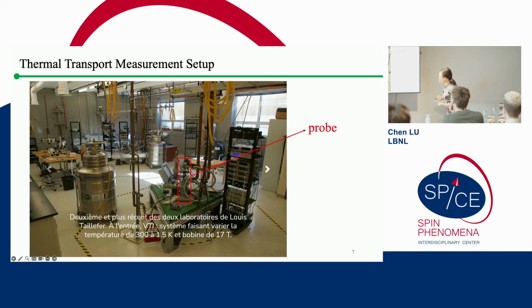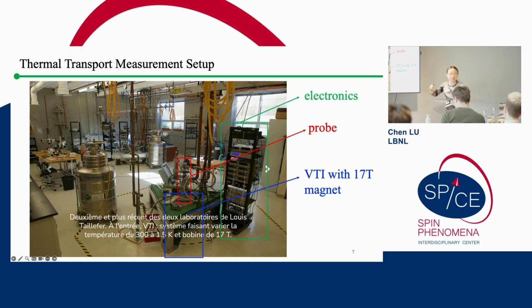For the type of system that we conduct our thermal transport measurement in, we usually use something called a variable temperature insert system, which is a cryostat that goes from 1.5K to 300K, and it is usually equipped with a very strong magnet, because we need a very strong field to actually distinguish a lot of the thermal Hall effect in the material that we try to study. And you put a probe inside the VTI and then apply field. And you also use other different types of electronics to help you read the signal. So this is just in general how the whole measurement setup looks like.